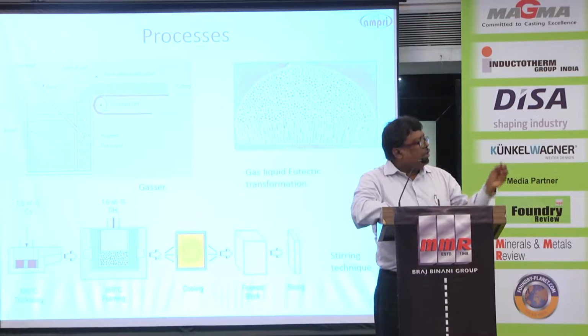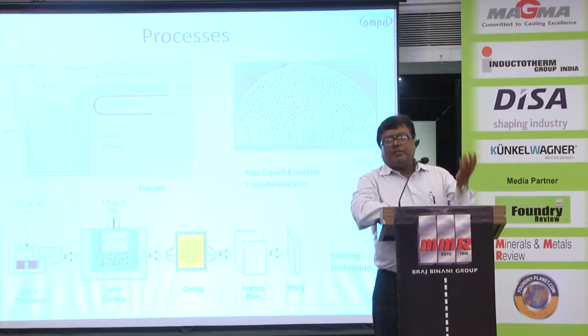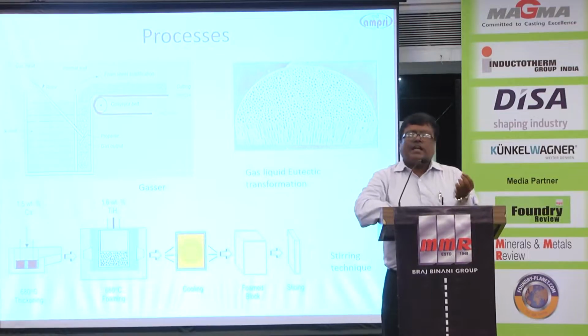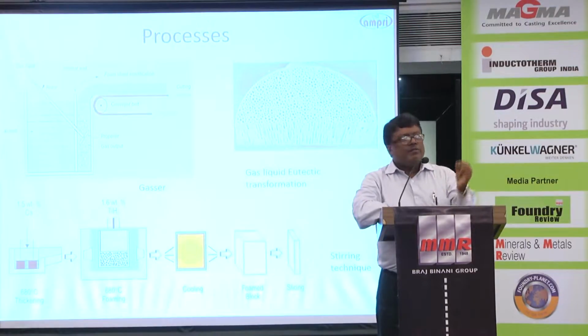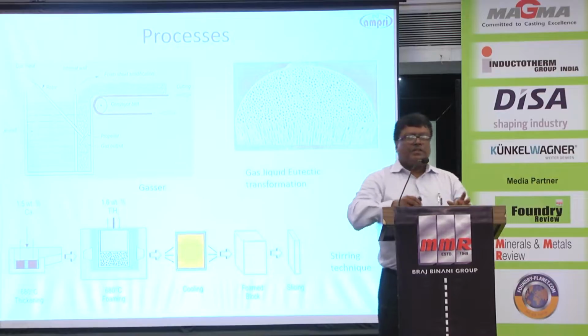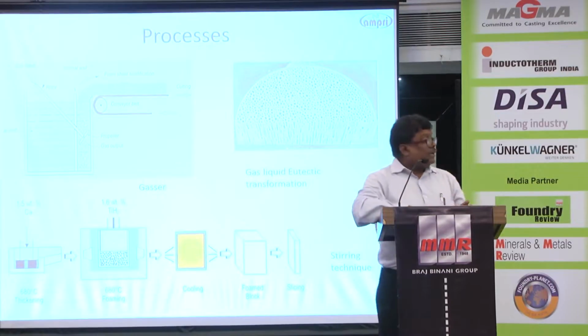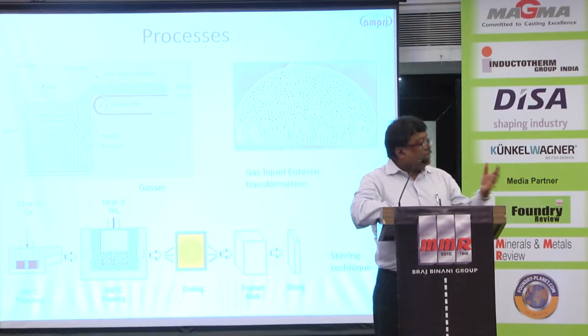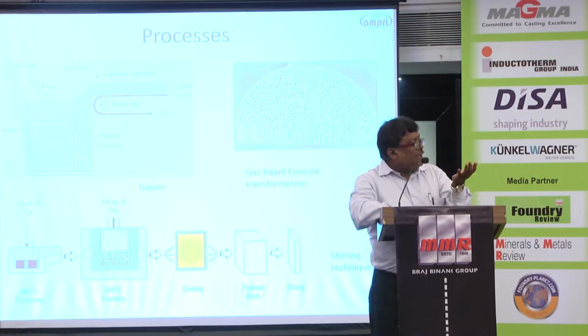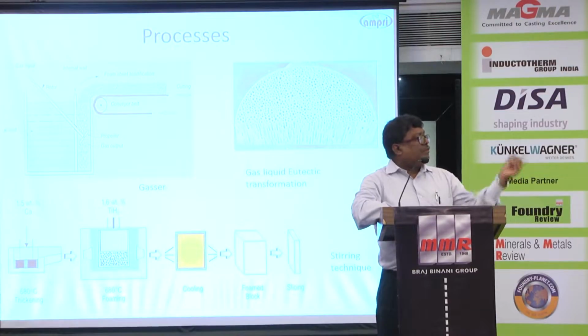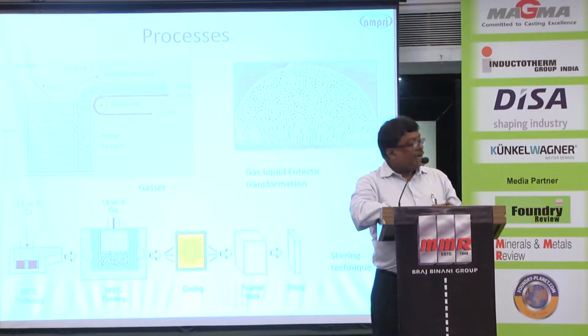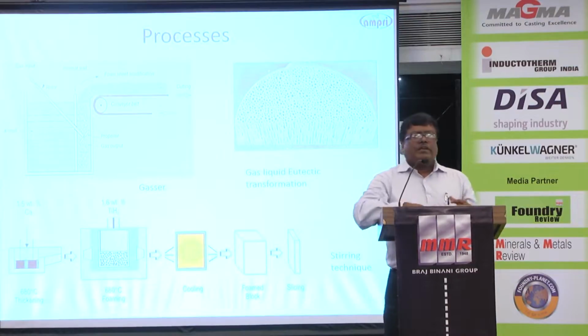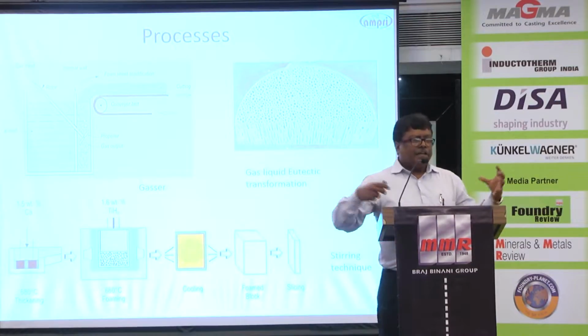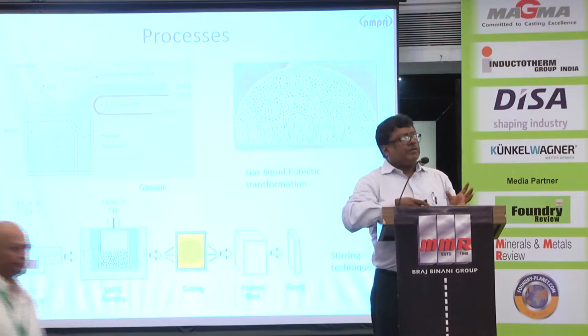Suppose you have the foaming agent, you can mix it with aluminum powder, make it compact, and then add it slowly into the melt and stir it so that it gets uniformly distributed within the melt. After adding the foaming agent, it will start foaming. At that time, this crucible should be taken out from the furnace, and it should be cooled at a very fast rate, either by spraying water or spraying air.